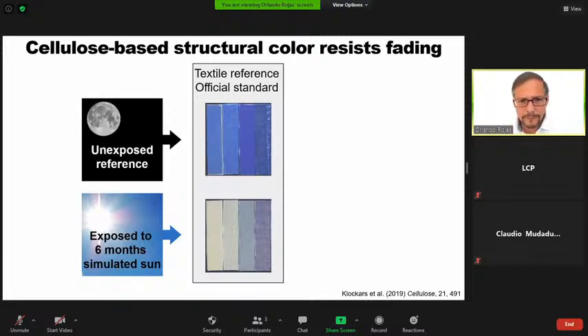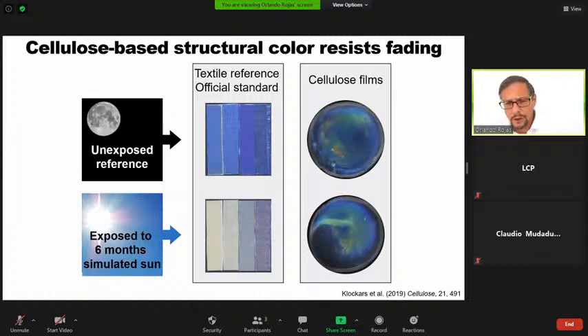But one of those aspects that I think is practical and very important is the fact that this structural color doesn't fade. And I was surprised when we wrote this paper last year that there was not really a demonstration of this effect of structural color resisting fading, at least not to our knowledge. So we took these coatings of cellulose nanocrystals and we put them on textiles. And we looked at simulated sun for 6 months to see what the effect of the sun is. And of course, in the case of typical dyes and pigments on textiles, they will fade with the sun exposure. But for the structural color that I show on the right, there is no effect whatsoever of the sunlight exposure. There is no fading.